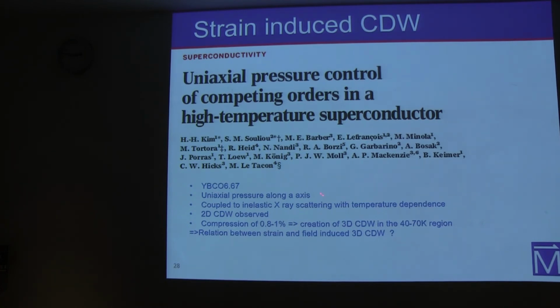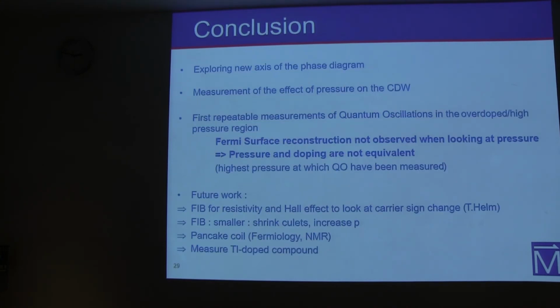So he found that upon uniaxial compression along one axis, the a-axis, you could still see the 2D charge order, but then by increasing the compression to the order of about 1%, you could recreate the 3D charge order, which was observed before only under high field. So here we have the question, still being investigated, between the strain and also high field. And one way that I look at my data is that maybe by applying hydrostatic pressure, at some point I get to a similar compression along the a-axis that also recreates a 3D charge order, which will also explain the quantum oscillations from that charge order and not something different than charge order. So this is where I am right now in our work.